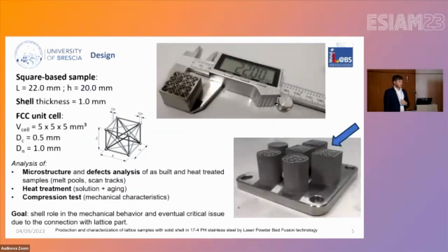For the design of the sample, we decided to print a basic geometry, such as a square-based sample with a length of 22 millimeters and a height of 20 millimeters, and with a shell thickness of 1 millimeter for the solid part. Instead, for the lattice part, we applied an FCC unit cell of 5 millimeters cube, connected with cylindrical struts and with a node connection spherical in shape. After that, we analyze in particular the microstructure and the defects of heat-treated samples and as-built samples. The treatment was performed as a solution treatment plus an aging treatment. After that, we also perform the compression test to understand the mechanical characteristics of this element.